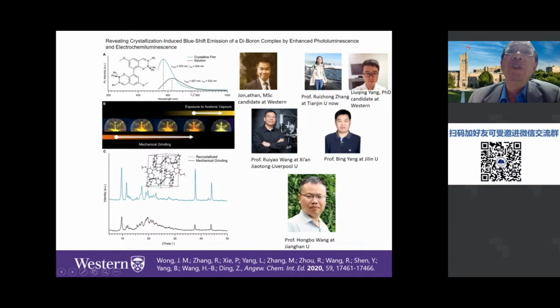So you can see these two photoluminescence spectra. This blue one is called crystalline film. So Jonathan and Professor Zhang and Liuqing Yang just made the film and then shone light on it. And then eventually we get this blue shifted photoluminescence. And if they dissolve the compound in a solution, like acetonitrile, then they observe a red shift. And the blue shift from this red is 67 nanometers. And you possibly are wondering what's going on. And I already mentioned that there's RIR, restriction of intramolecular rotation.